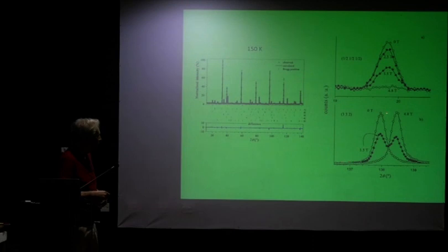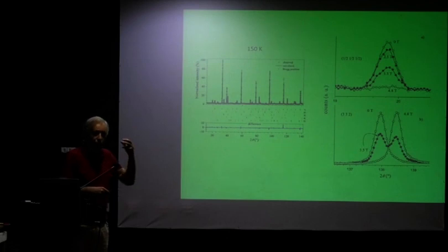So what happens is that when you're sitting at 0 field, this is your peak. It's sitting at this value. And then at an intermediate field of 3.5 Teslas, shown with these black dots here, you see that the intensity related to the volume in the antiferromagnetic phase is getting smaller.